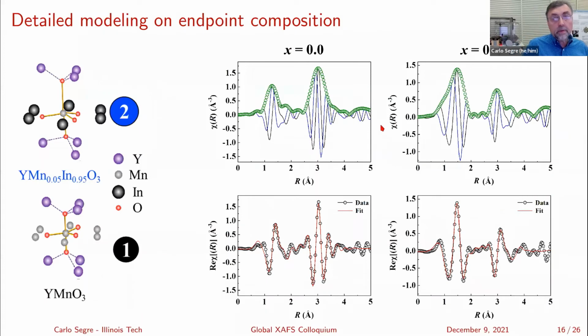Then we fit the EXAFS, and we realized that we could get very good fits of the EXAFS data for the endpoints, x equals 0 and x equals 0.95. This is the magnitude of chi of r, and here is the real part of chi of r. You can see that over a wide range, we fit it out to almost 4 angstroms, so several shells out or longer paths. We get very good fits for these 2 data points. Then we decided, okay, we have the 2 endpoints. We'll now try to fit all the other spectra as linear combinations of these 2 models, not changing the models at all. We left these models constant and just used them with 1 parameter to fit all the other data sets. That's what I'll show you next.